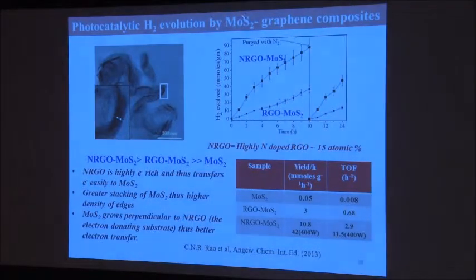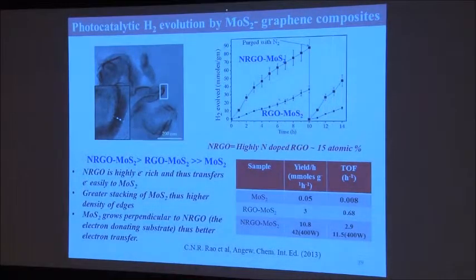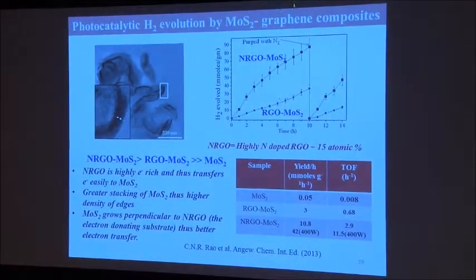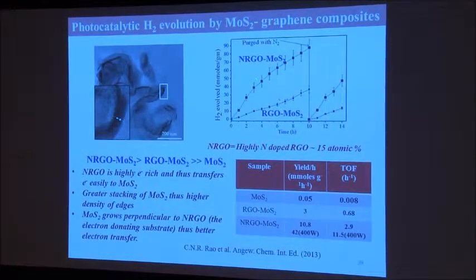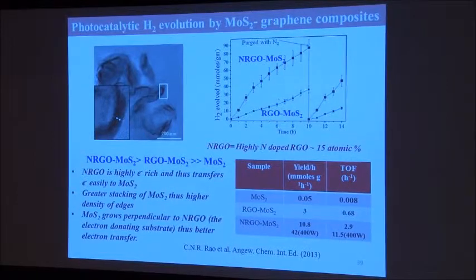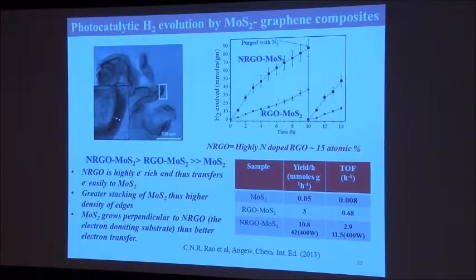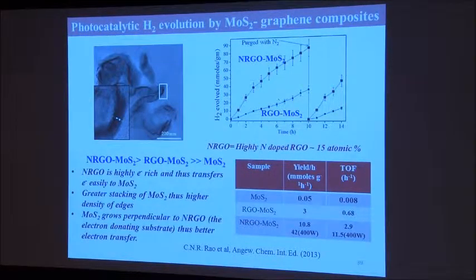What they do is make a composite of molybdenum sulfide with graphene. So we also thought we will do that. We took molybdenum sulfide and made a composite with reduced graphene oxide. The amount of hydrogen given is not very high. So we thought, well, what is happening is graphene is acting as the electron channel for molybdenum sulfide—it gives electrons. The protons go on the molybdenum sulfide surface, the electron comes through graphene, and those electrons reduce the proton into hydrogen.